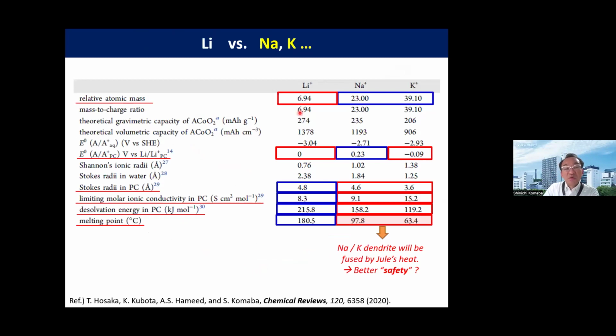In particular, when we compare lithium, sodium, and potassium, of course, the atomic mass is heavier for sodium and potassium than lithium. It is quite disadvantageous. However, the standard electrode potential E0 for potassium is lower than lithium. This means that a wider potential window can be achieved for the potassium system. And also, as I mentioned, the Stokes radii are smaller for sodium and potassium compared to lithium.